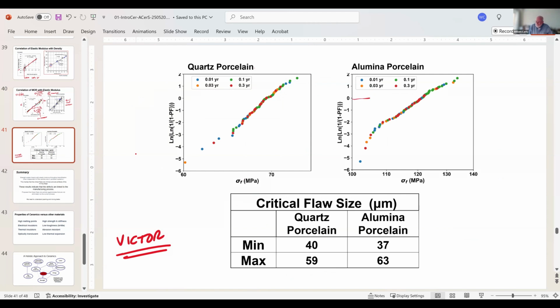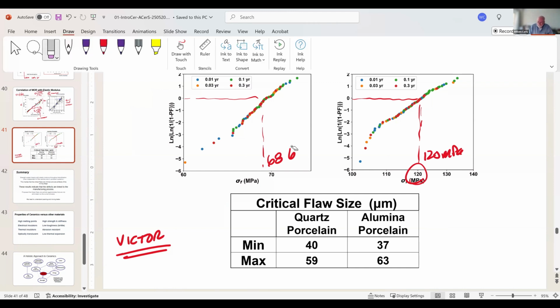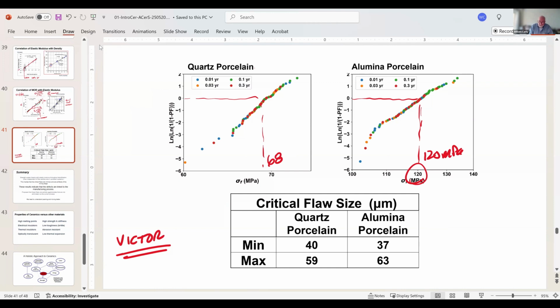So if you go in here and you go to 0 and you look at the strength, this is right about 120 megapascals. And you go in here and you look at 0 and you look at the strength. This is somewhere right around about 68 megapascals, okay? So you would come back and say right away, oh, the alumina porcelain is stronger. And I would say you are correct, okay? So the strength of the alumina porcelain is greater than the strength of the silica porcelain, or the quartz porcelain.